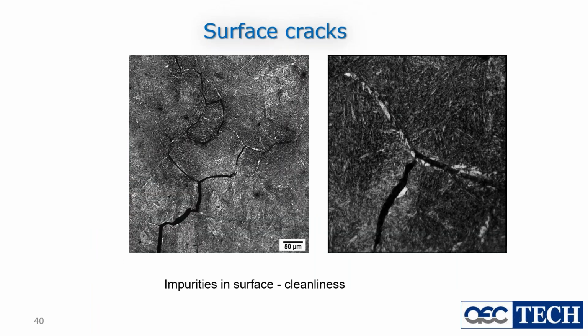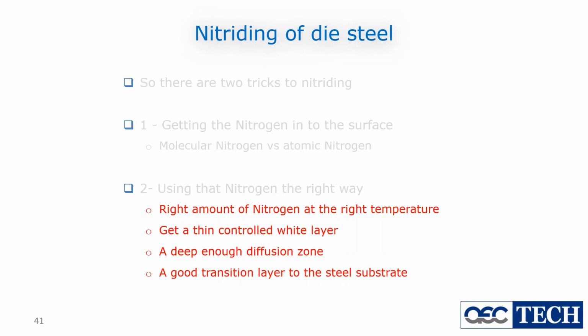We can also get this. This is fairly high magnification of the surface of the die. These are cracks which are caused by cleanliness issues in the die. This is where the compound that's on the die is itself diffusing in the die and causing problems. So we really need, cleanliness is really next to godliness.